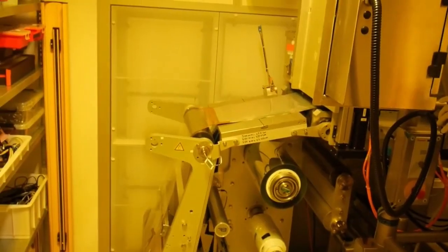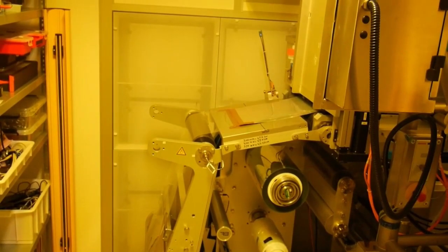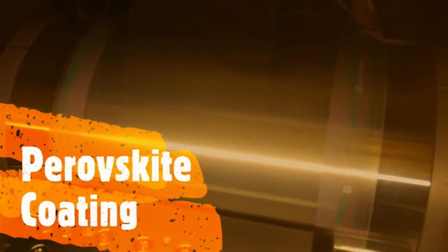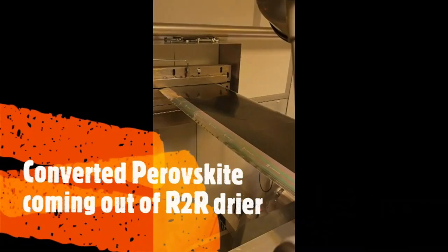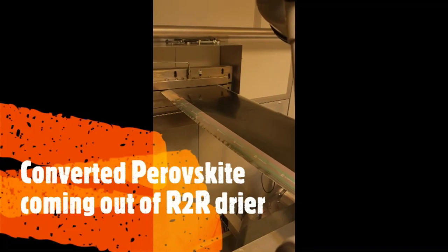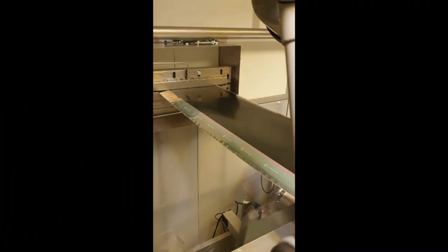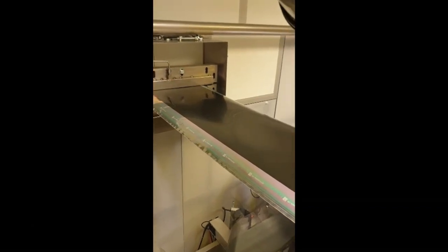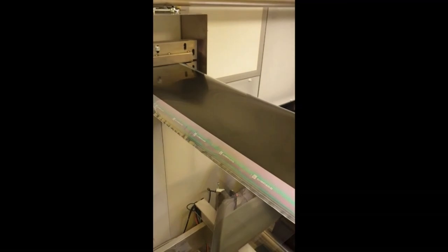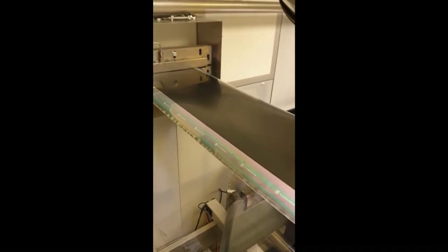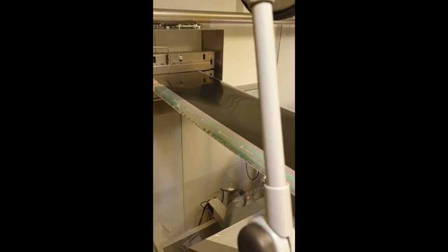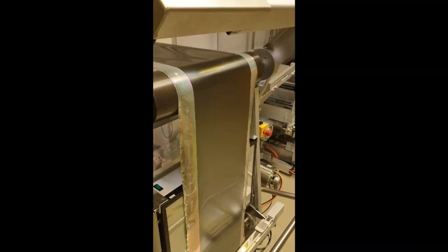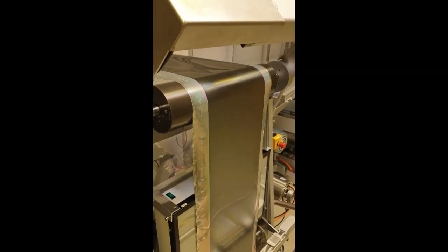Here we see that the substrate, the flexible substrate, in this case an aluminum foil, is entering the roll-to-roll line. It passes through, along the slot die coater that's shown here, where we deposit an ink with the perovskite precursors, and this is entering then the oven. And when it returns from the oven, the perovskite precursor is actually converted in a perovskite layer. You see this dark, nicely light-absorbing layer that is coming back from the oven, from the furnaces, and is then rewinded in the setup.